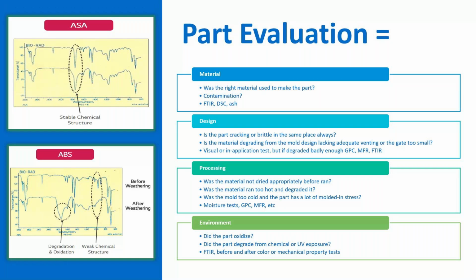But if you degrade it badly enough, you could do stuff like GPC. You could do your melt flow to see if you're seeing a molecular weight change because of it. You could do FTIR. Maybe you're getting the contamination problem, or they weren't using the right material, and you had designed it for ABS and they ran something else. Whatever it may be, we could use those tests, or a combination of them, to see what might be going on.